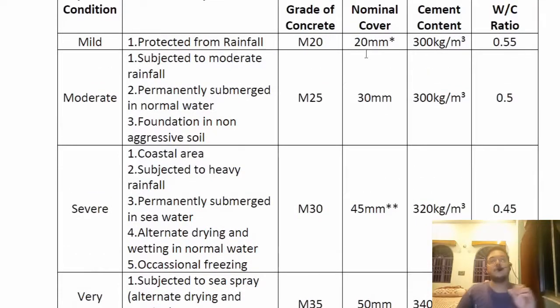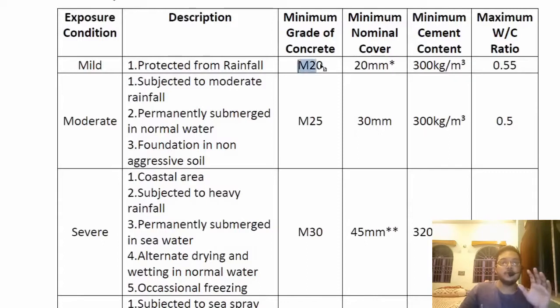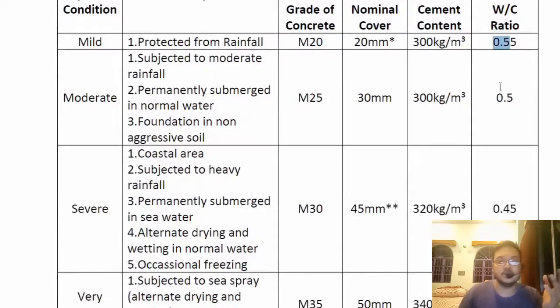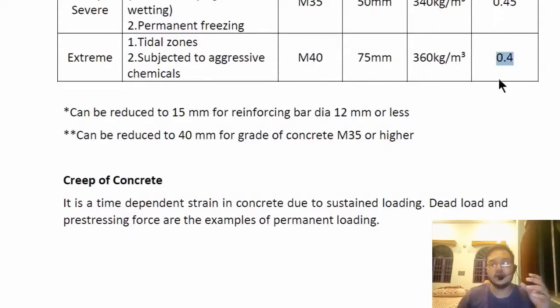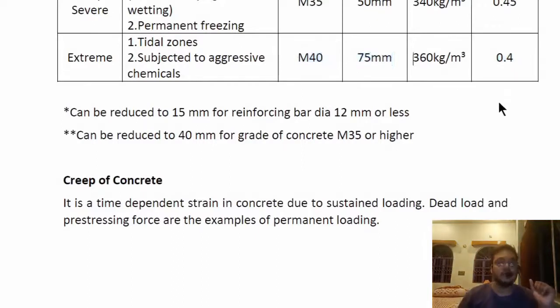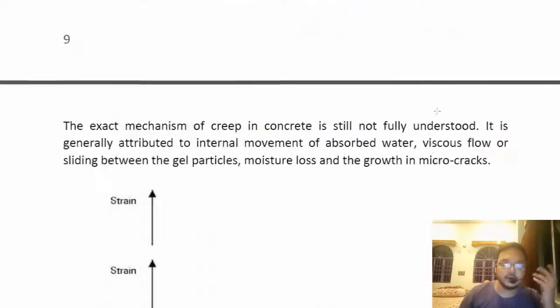So now, you should be well aware of this particular table and what grade of concrete uses what water to cement ratio. As we had M50 in that particular question, I had assumed one value which is different from this 0.4. You can see that for M40 it is suggested to be 0.4. In our question the grade of concrete was M50, so I took a water to cement ratio which is actually lower, that is 0.35.